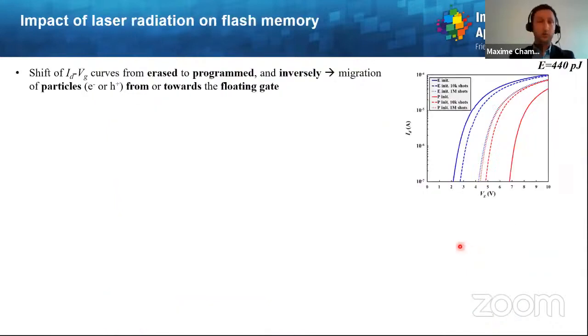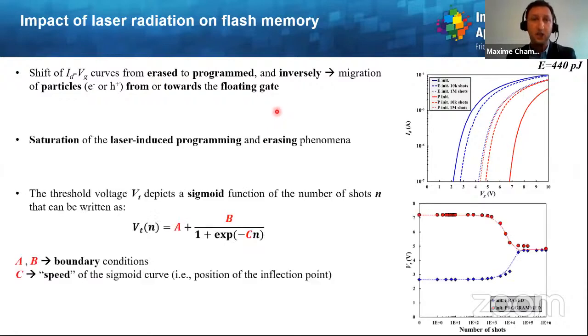So then when you perform some laser irradiation of the flash memory, here are the results. You start here with solid blue and red lines, either erased or programmed. And you can see that there is clearly an effect of the laser radiation after 10,000 shots and 1 million shots, which means that there is a migration of particles, either electrons or holes, from or towards the floating gate. Then when you repeat this for different numbers of shots, here I represent the threshold voltage as a function of the number of shots, and you can see that the laser-induced programming and erasing phenomena are somehow saturated, here around 5 volts.